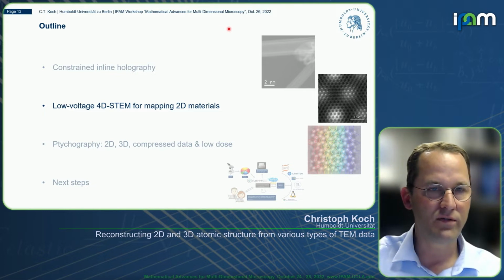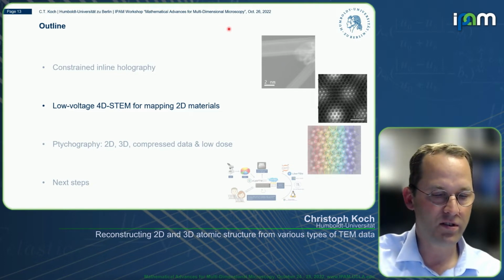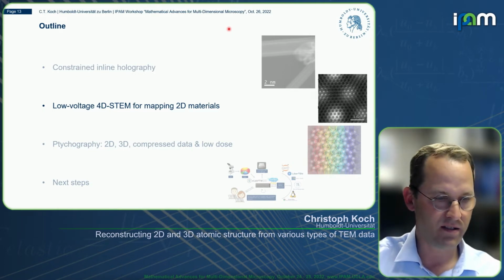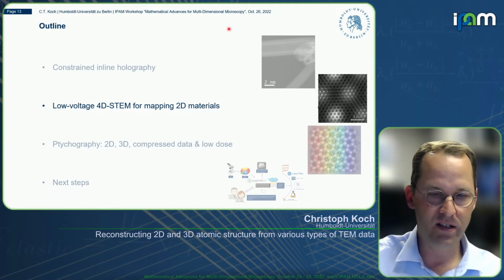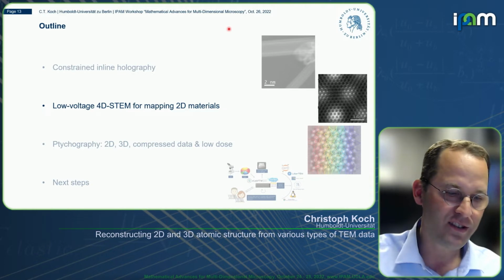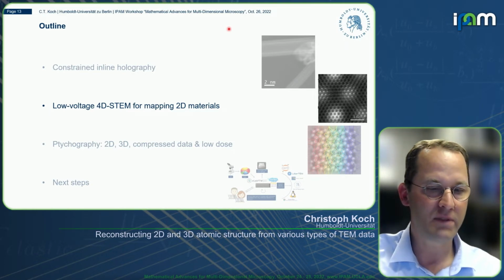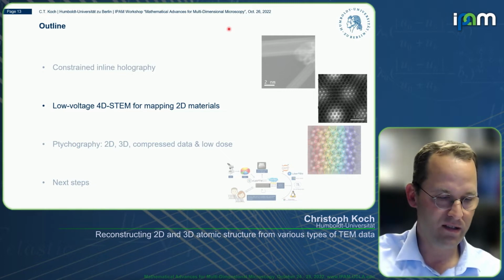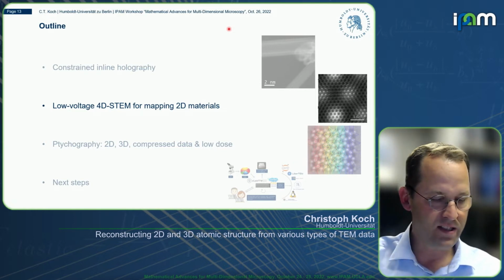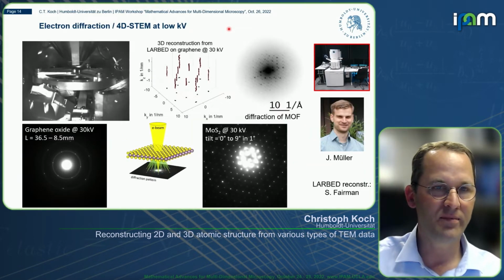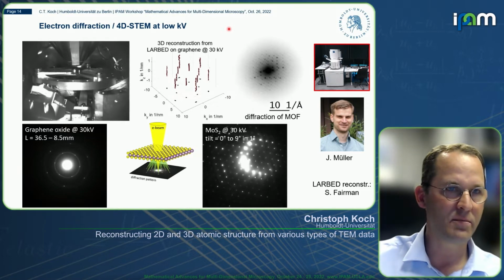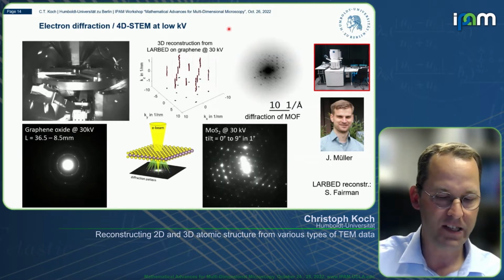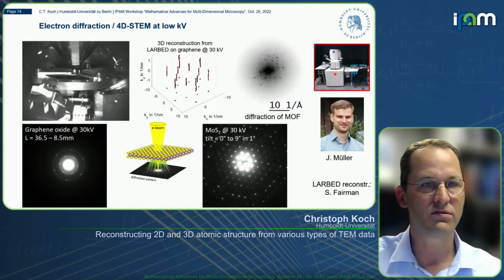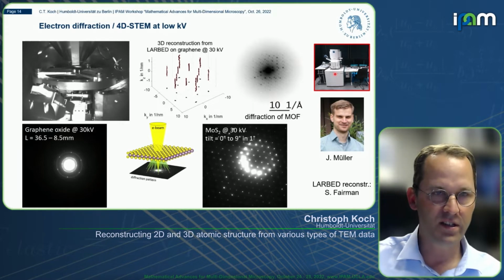But coming now to low voltage, that was a very special microscope, which was a TEM. But now we want to go more into the business of scanning, as has been very much a current trend, that scanning transmission electron microscopy seems to be much more preferred over wide field illumination microscopy in TEM. So this is a scanning electron microscope that operates at low voltages. It has a maximum of 30 kilovolt, and it can go down to, let's say, 1 kilovolt and even less.